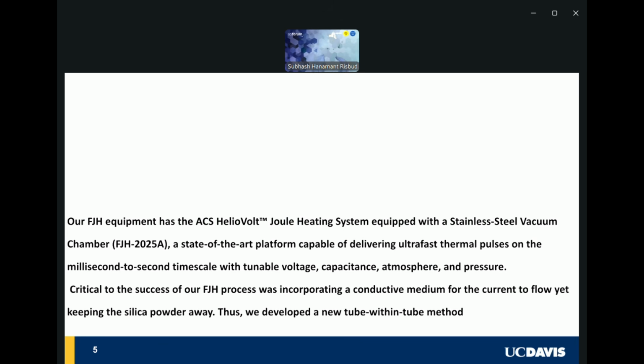So our equipment for the flash Joule heating is a Joule heating system equipped with a stainless steel chamber, a platform delivering ultra-fast thermal pulses with a tunable voltage and all of this. But critical to it is the conductive medium. So because silica is insulating, we developed a method in which we put 2 tubes, one inside with the silica in it, and the outside one contains graphite or something which can conduct. So that's kind of the start of the process. And here's what we kind of physically see when that happens. This is the flash Joule heating.